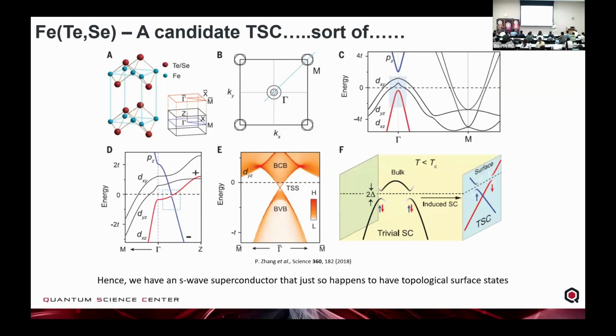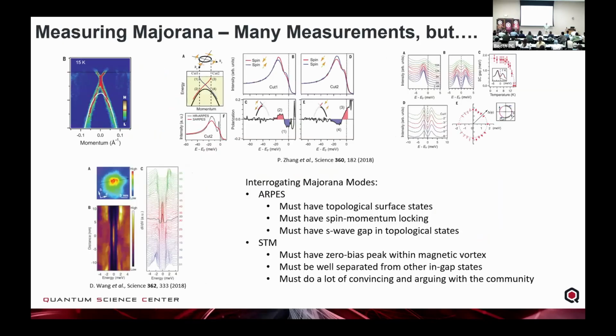Here's where it gets interesting, because as you start doping tellurium in for the selenium, you change that spin orbit coupling. At a certain doping, at about 50-50 doping, these pz bands will get pulled below the Fermi level and you'll create a band inversion. The band inversion from this spin orbit coupling will create topological states. With these topological states, bulk boundary correspondence, you have a Dirac cone that will appear on the surface. Now we have an interesting situation where you have a trivial superconductor, but on the surface you have these topological surface states. So this in itself is a candidate topological superconductor.